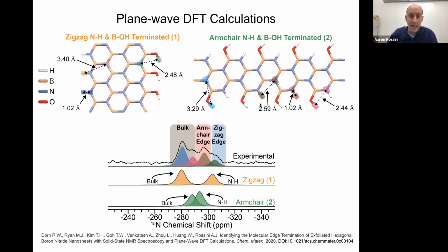The edge nitrogen atoms are predicted to occur here at a slightly different chemical shift from those of the zigzag. And then the bulk nitrogens, those ones that are the first layer in from the edges, those are predicted to occur there. So this nicely explains the nitrogen 15 NMR spectrum that we see.